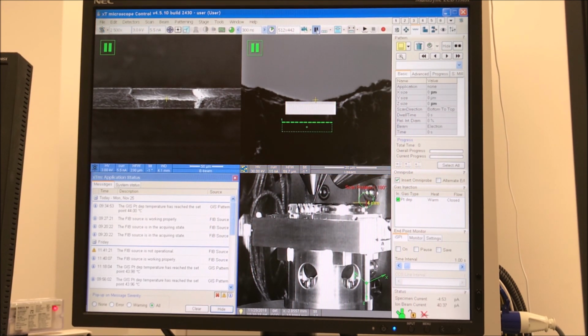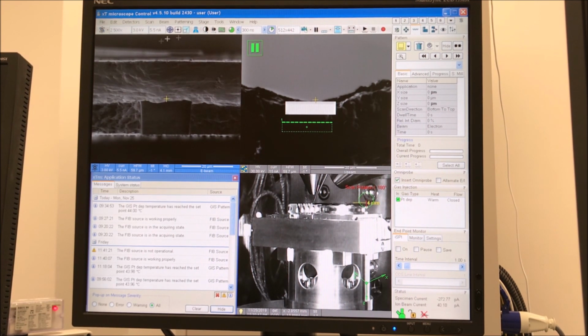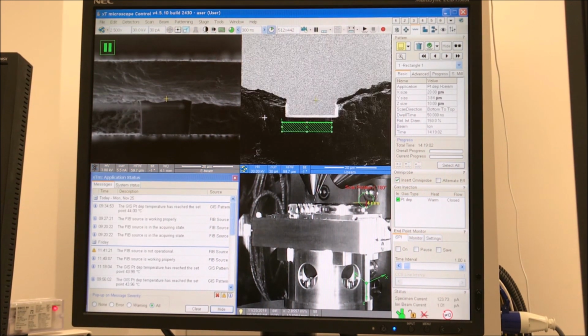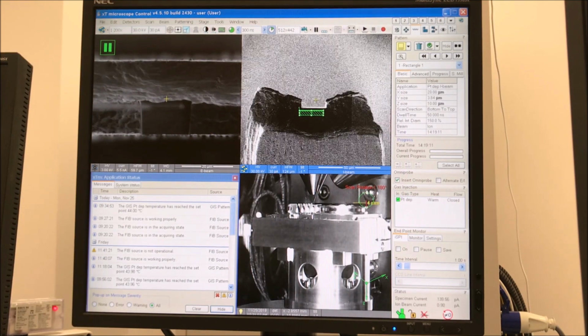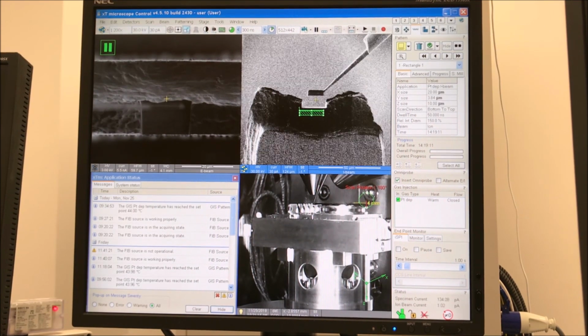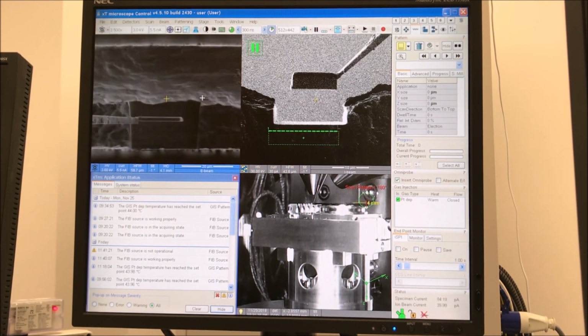So now that the shelf has been cut, I reduced the ion beam current to 30 picoamps, and now I'm using E-beam and I-beam imaging to position the lamella at the edge of the shelf for attachment. You want to make sure when you attach the lamella to the shelf that you do it right at the edge of the shelf that is closest to the middle of the post.